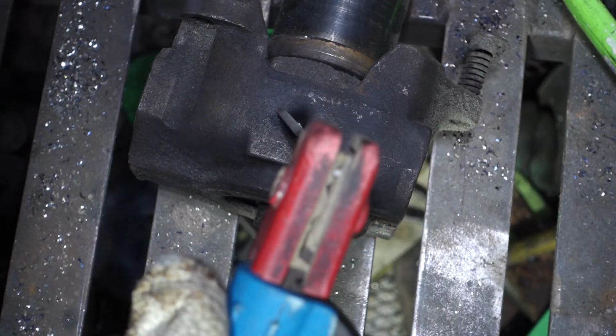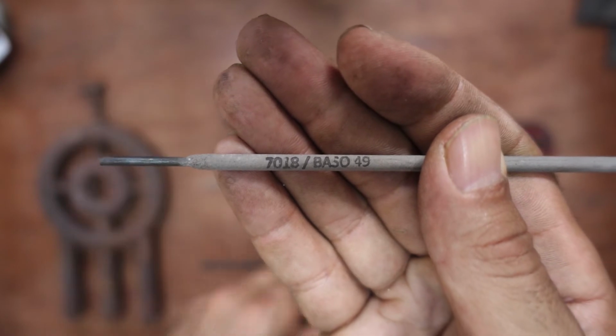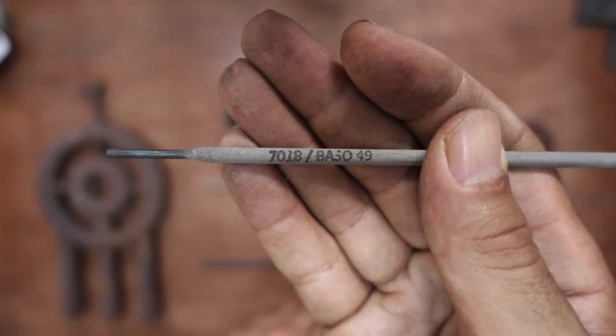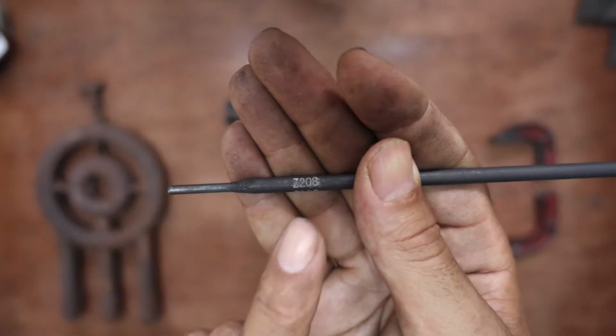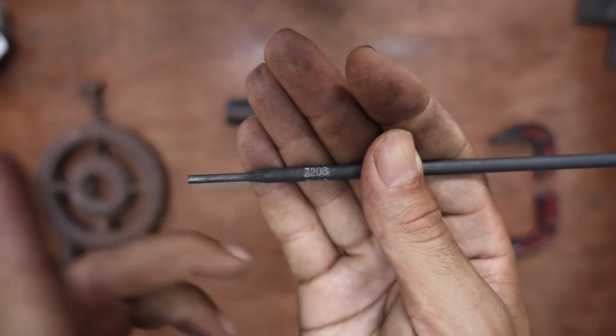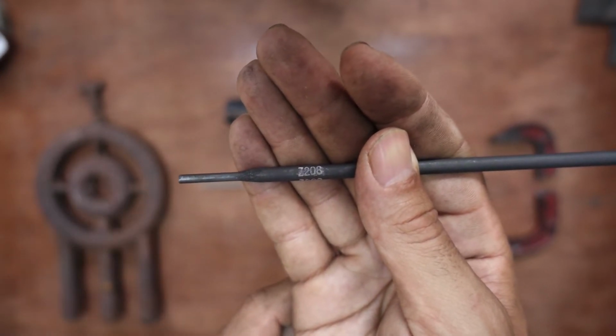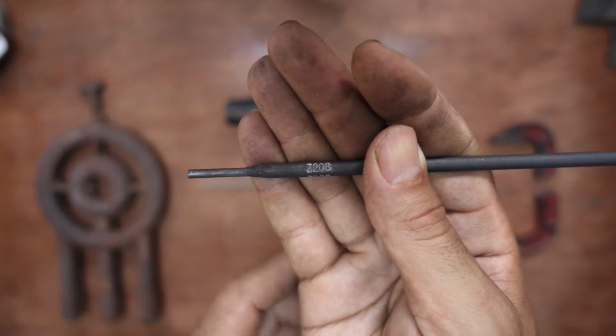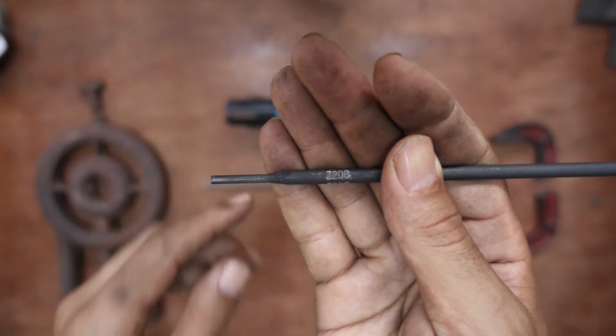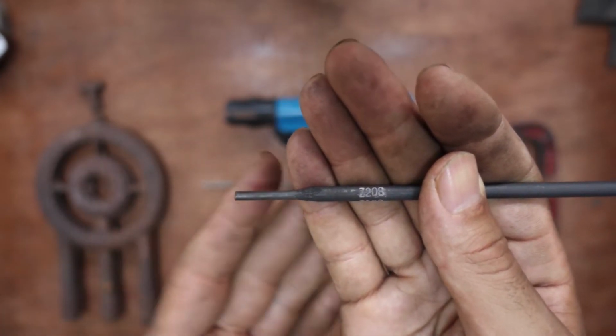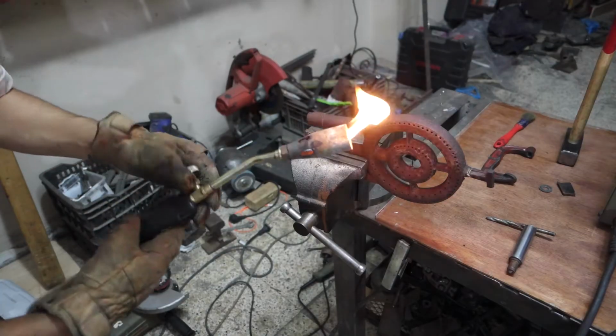Don't use 6013 when stick welding cast iron. The reason is that it splatters too much and sometimes even explodes a bit, and I never got a good weld using it. Unlike the 7018, it is a good all-around electrode. But first, I will use this Z208 that produces a cast iron weld if it's been treated right. But the problem with it is that it gives a brittle weld that could crack easily.